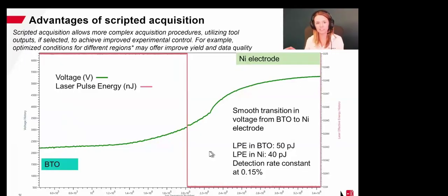So in this case, I'm showing the voltage evolution, so the voltage curve as we are acquiring data as we go from our barium titanate ceramic to our nickel electrode. So in this case, we've flipped around our sample prep so that our ceramic is on top. Now in this case, we've chosen a set of acquisition conditions for barium, which is not the same as our nickel electrode. But as we change those, we can see that our voltage curve was quite smooth throughout that transition zone as we go from one material to another because we are dynamically changing those conditions to be most appropriate for those materials. Now, what we don't want to see as we go through interfaces are really sharp transitions. That can affect our reconstruction, and that can affect our confidence in being sure that we've actually collected and not broken through our interface. So by using scripted acquisition, we can choose appropriate acquisition conditions, reduce the stress on the specimen and lead to higher success rates through interfaces.